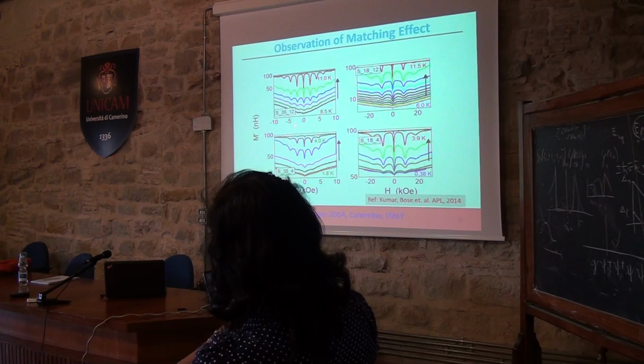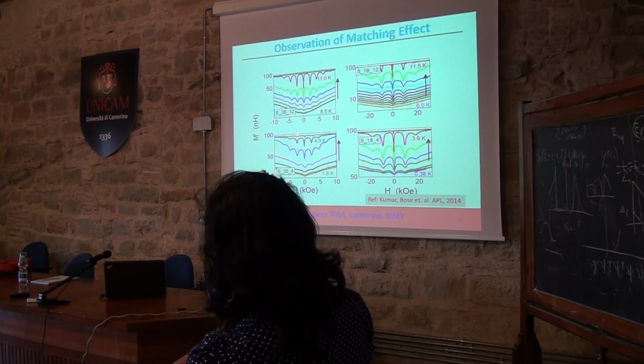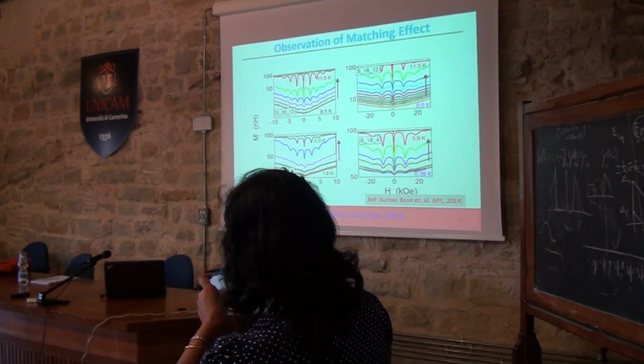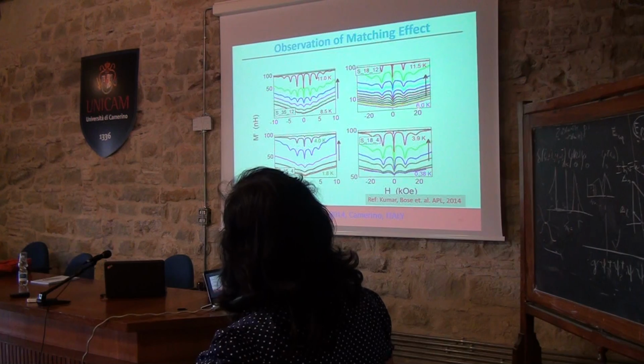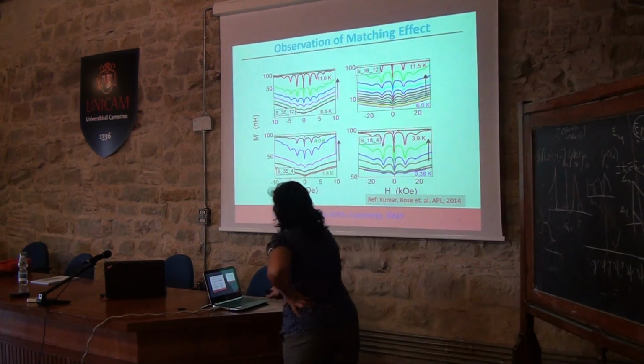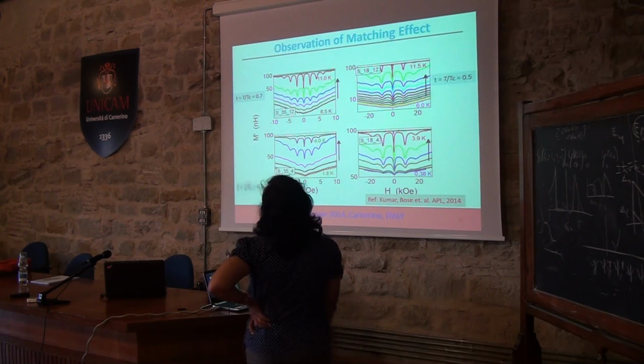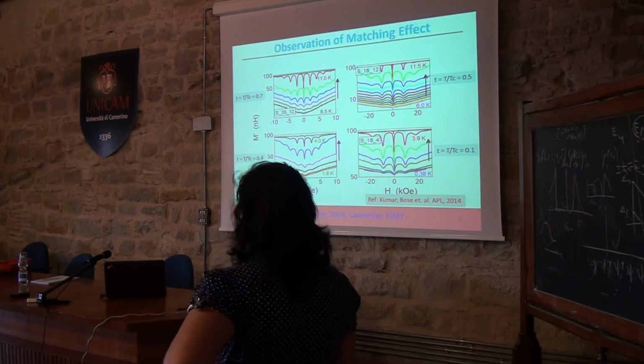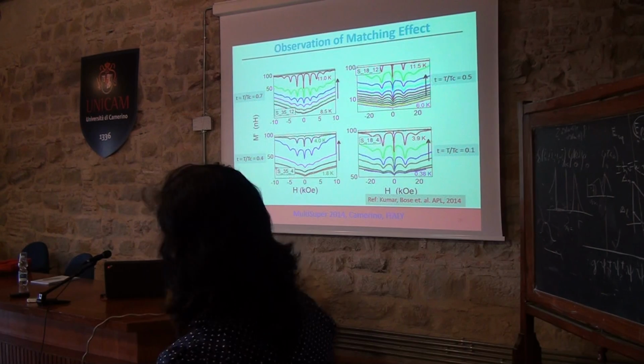This is the sample for a 35 nanometer pore diameter, and you can see 4 periods in this sample, while in the sample with an 80 nanometer pore, where you increase the pore diameter, you see only 2 oscillations. The other important feature which you can see here is that the oscillations survive to much lower temperatures.